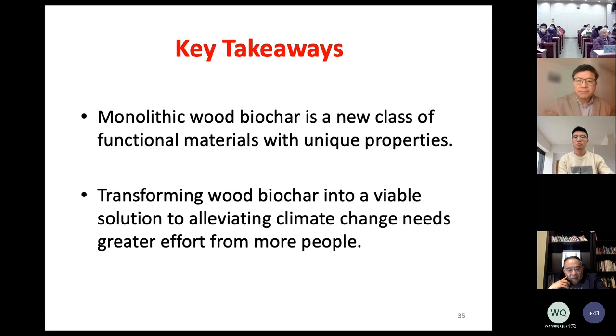Thank you. I think you actually touched on two things, right? One is the specific surface area. It's actually extremely critical because as a physical device, the double layer is formed on the surface, so its capacitance is proportional to the specific surface area. But on the other hand, in order for the capacitor to work, that specific surface area has to be accessible, meaning that you have to have the right combination of macropores, mesopores, and nanopores. Nanopores actually provide that specific surface area.